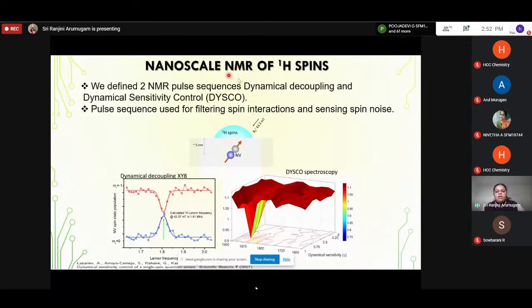So we have done some nanoscale NMR of proton spins using optically detected magnetic resonance. We took the NV diamond, which is buried about 5 nanometers from the surface, and took a water bath of ultrapure water, which is nothing but proton spins, and applied an external magnetic field of about 43.3 millitesla. This experiment is not done by the regular NMR sequence. We define two different pulse sequences. One is called dynamic decoupling, and another is dynamical sensitivity control, abbreviated as DYSCO.